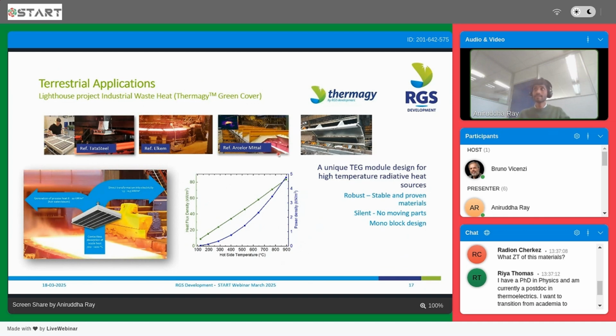One of the key learnings we had from this application was that generating electricity was part of the picture, but the other fact is that at the back of our TEGs, we could also generate a lot of good quality process heat, so up to 8 to 20 kilowatt per meter square of hot water and steam, which can be reused in the industry. So with this combination, they get a double benefit from such TEG modules.